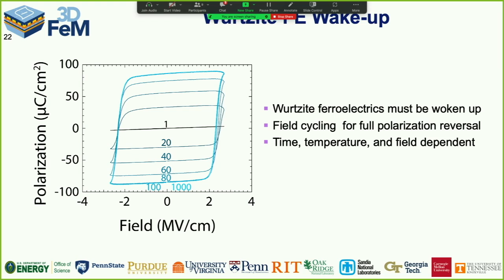The other thing that we see is that very often, the first time we try and switch one of these, it looks like a beautiful linear dielectric. And we actually have to switch it a couple times before the polarization starts to reorient. This material undergoes a process called wake-up.